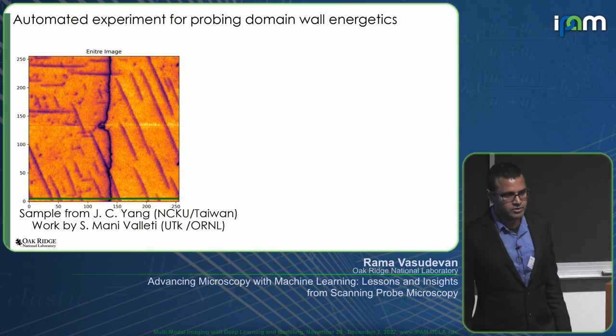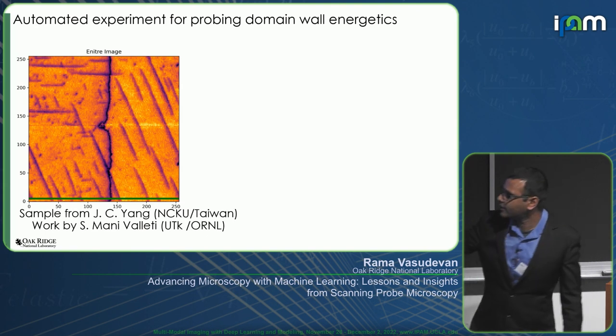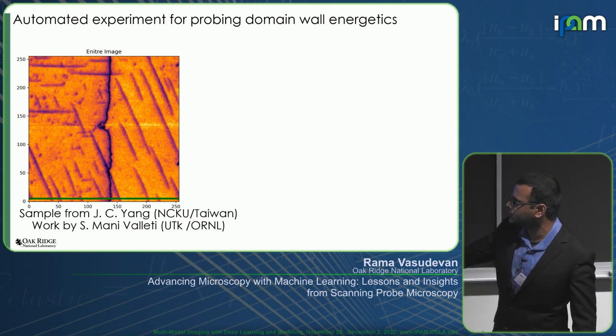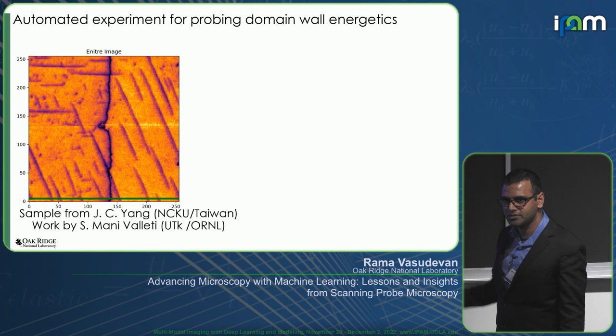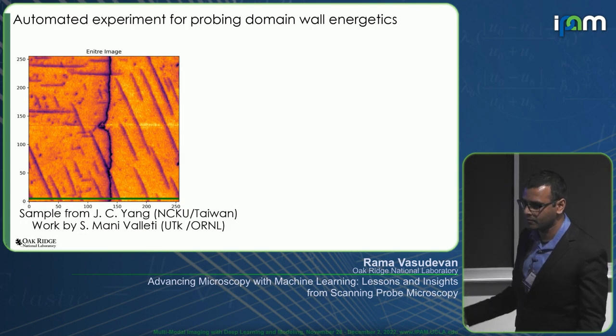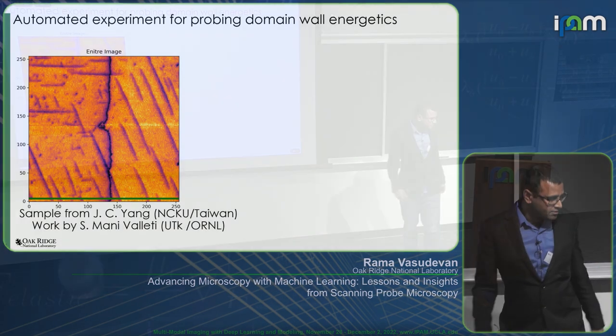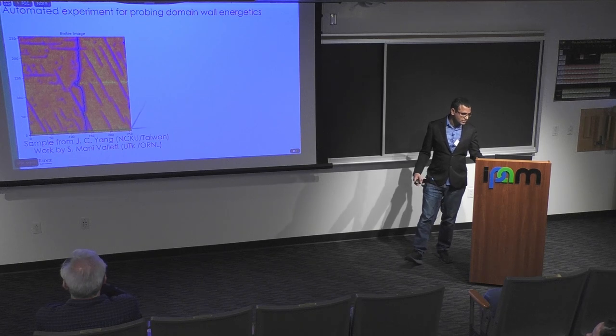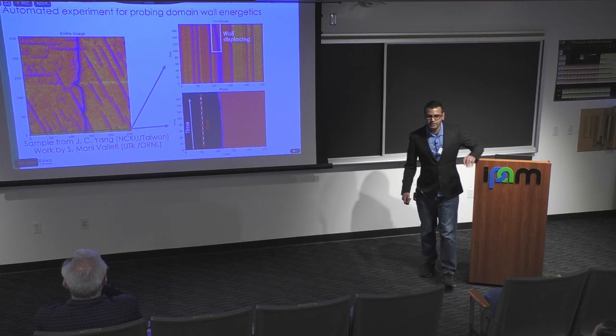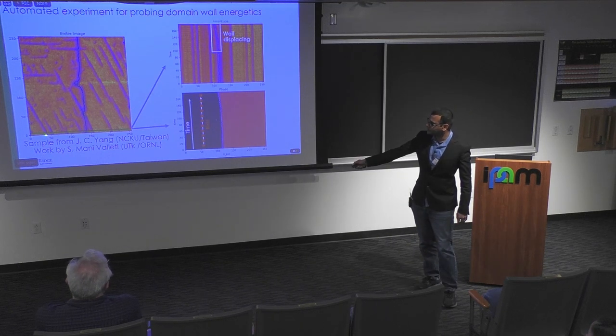So how would we do that? Typically, you would position your tip at different positions, apply a particular voltage pulse, and then go image it, and you can get some data this way. But now, because we have an automated system, we can get a huge amount of data. For example, we can choose a line.